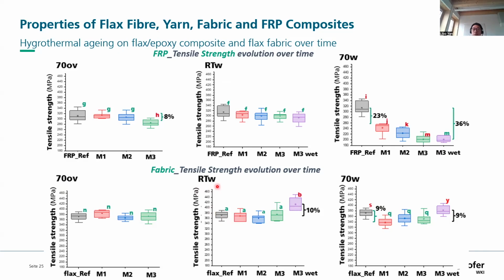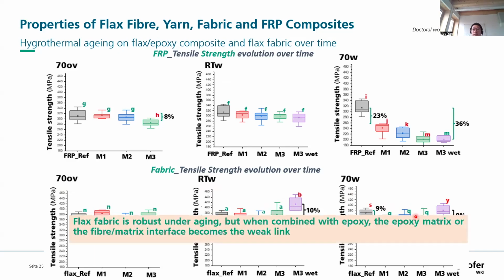For the flax fabrics exposed to water at room temperature, after 3 months there's even some increase. For the flax fabrics exposed to 70-degree hot water conditions, there are some fluctuations in the property, but the change was quite small. So that's why we can make a conclusion here. Flax fabric is quite robust under hygrothermal aging, but when the fabrics are combined with the epoxy matrix, the fiber polymer matrix interface becomes the weak link.